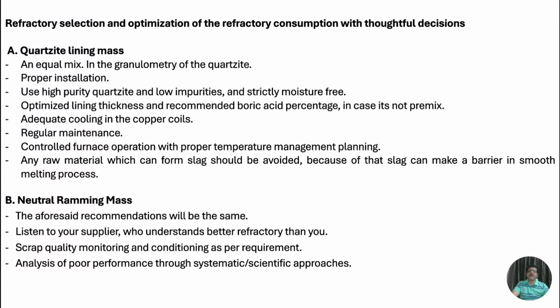Refractory selection and optimization of refractory consumption with thoughtful decisions. Quartzite lining mass: an equal mix in the granulometry of the quartzite, proper installation with high purity quartzite and low impurities, and strictly moisture free. Adequate cooling in the copper coils. Regular maintenance. Controlled furnace operation with proper temperature management planning. Any raw material which can form slag should be avoided. Because of what? Because slag can make a barrier in the smooth melting process.